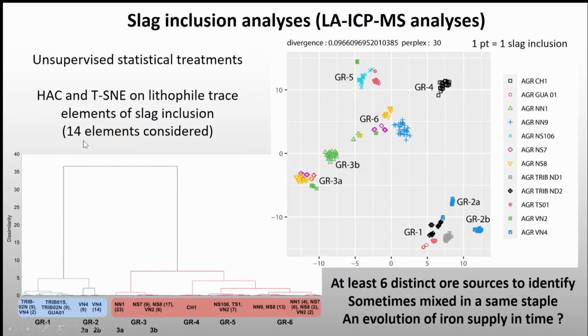So we use, for example, hierarchical clustering and other analytical treatments, which actually show the same thing. They show here that we have groupings of different slag inclusions which have compositions which are close. Sometimes we have close compositions which belong to two different staples, such as here the pink one and the yellow one. They have the same composition. Here the black one is alone on its side.